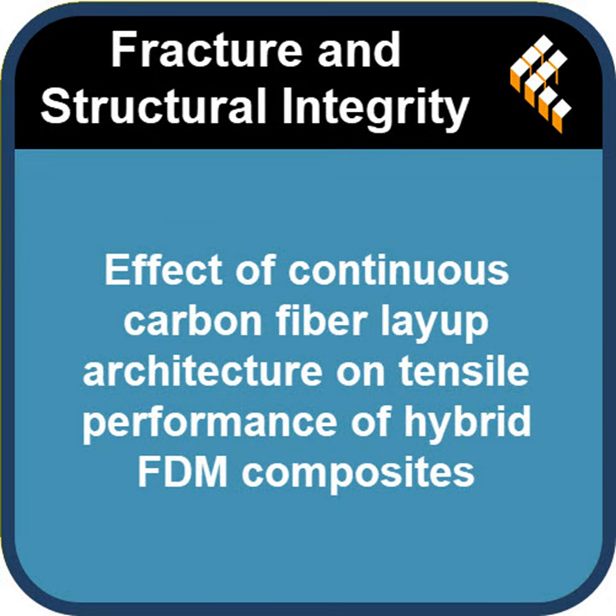Really? How much difference does the direction actually make? Like if I'm printing a part, does angling the fiber by a few degrees change the structural integrity that drastically? Oh, it completely transforms it. The researchers tested laying these continuous fibers at angles of 0, 30, 45, and 60 degrees relative to the direction the material gets pulled. Okay, so what happens at 0 degrees? So at 0 degrees, where the fiber is perfectly aligned with the pulling force, the stiffness skyrocketed to over 40 to 60 gigapascals. Wait, isn't that approaching the stiffness of aluminum?